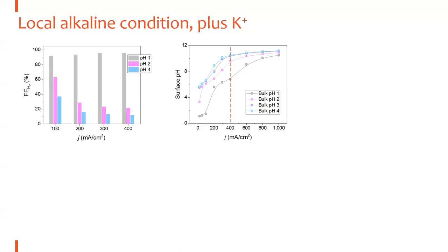If we look at the dashed line, we modeled the pH at different current densities and different bulk pH. At the same current density, if we have a more acidic bulk pH, we will have a more acidic local environment, with the pH only around 6. But if we have a less acidic bulk pH, we will have a much higher local pH, which is around 10. So this may explain why at higher pH we observe reduced hydrogen evolution, but at pH 1 we do not.